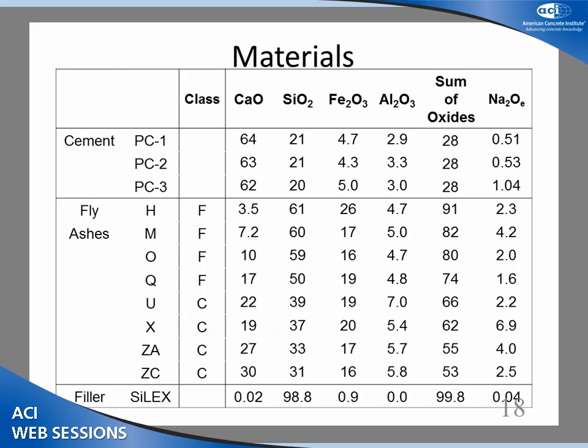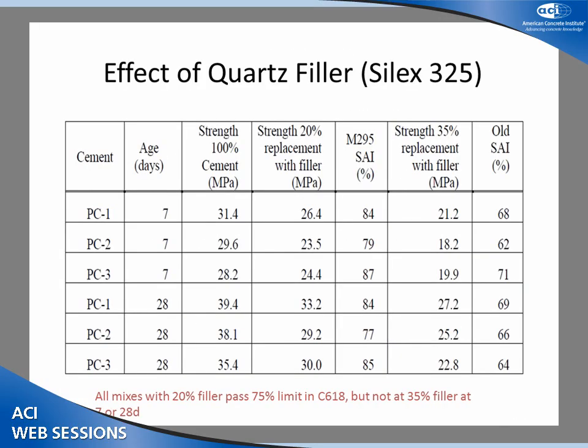We did some testing. I did some testing together with Larry Sutter a few years ago on a pooled fund study, and here we used a quartz filler. We used it with 3 different Portland cements, and we tested it relative to 8 different fly ashes, C's and F's, and we looked at the strength activity index, and this is just with the quartz filler.